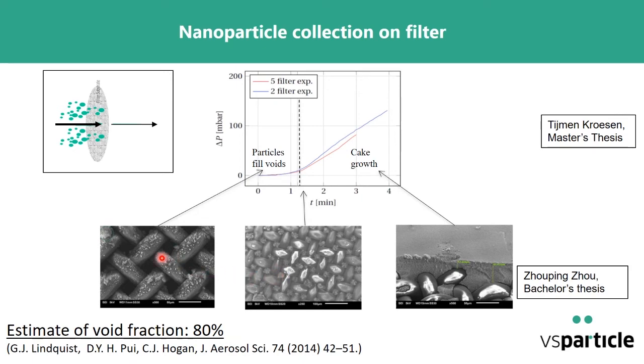And you see here micrographs of a filter where only very few particles have been filtered, and here is the stage where the pores in between, the voids in between, have been filled. And after that, you get a cake formation on this filter. So this is the porous material that is caught on the filter, and you can make the layer basically as thick as you want. And it has a void fraction, which you can estimate that is around 80%. So it could almost be called an aerogel. It's a very porous material.